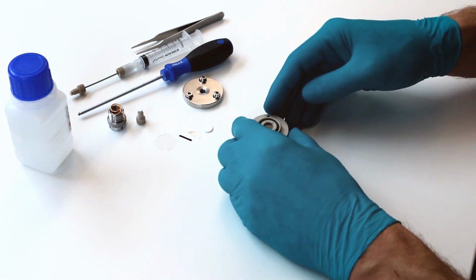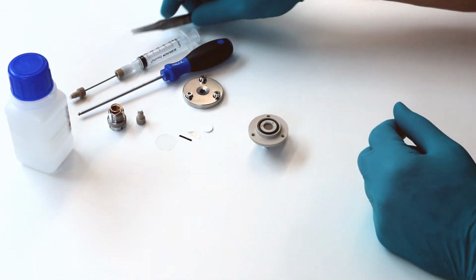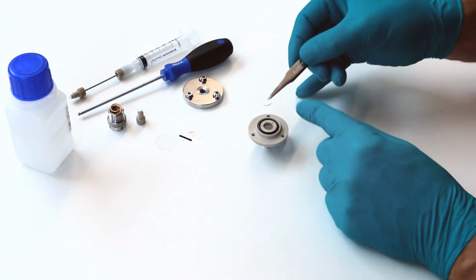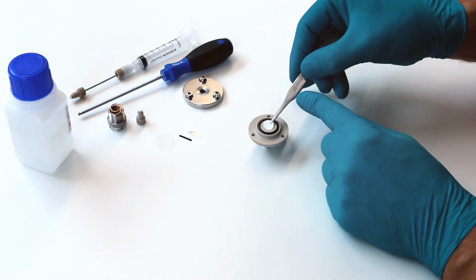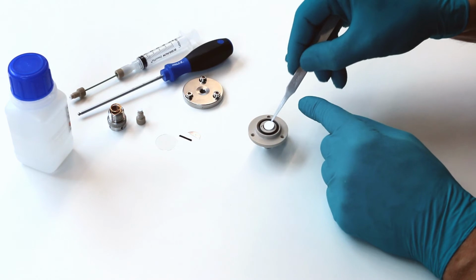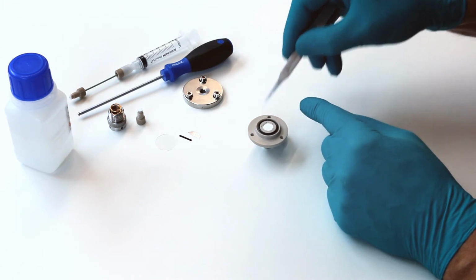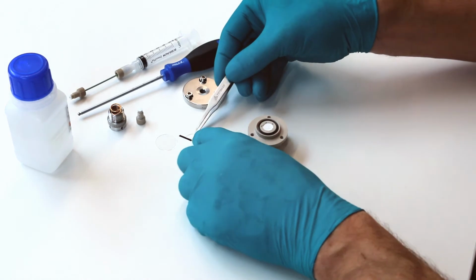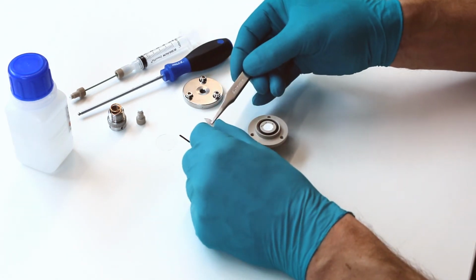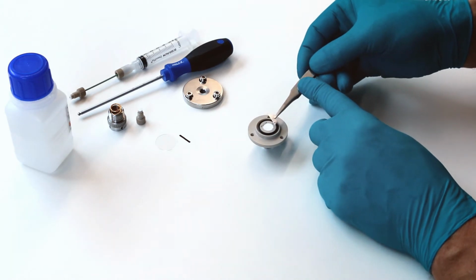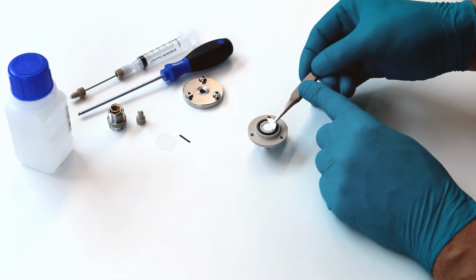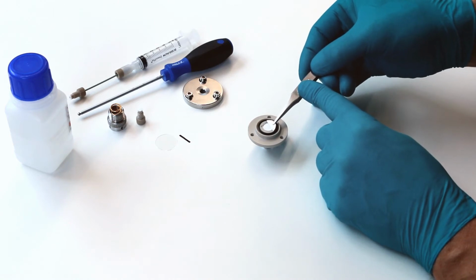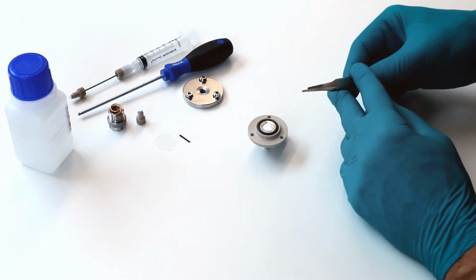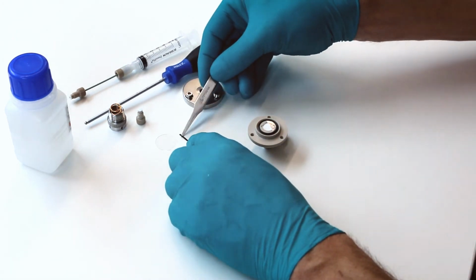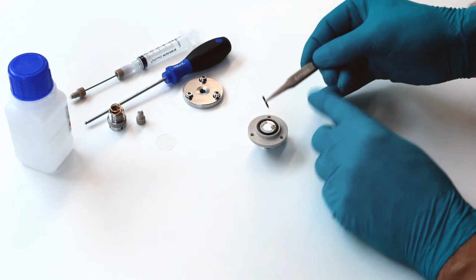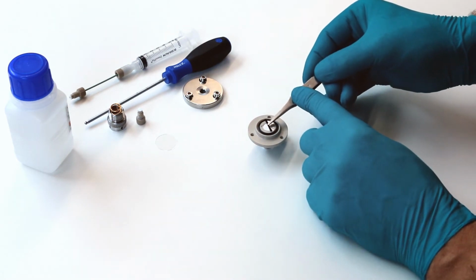Put the assembly onto the desktop. Insert this glass fiber separator, which is 1 mm thick and 10 mm in diameter. Place the lithium metal foil onto the separator and make sure that feed wire B makes the contact at the edge of the lithium metal foil.